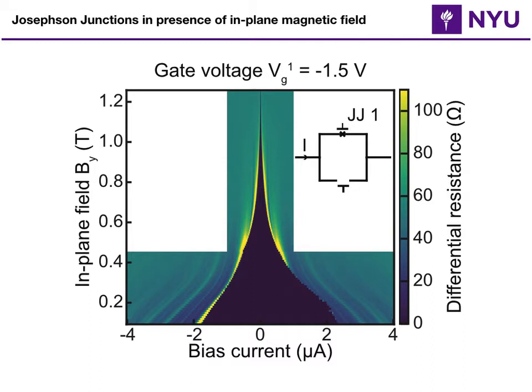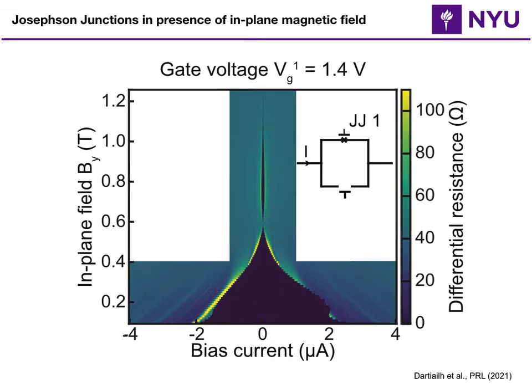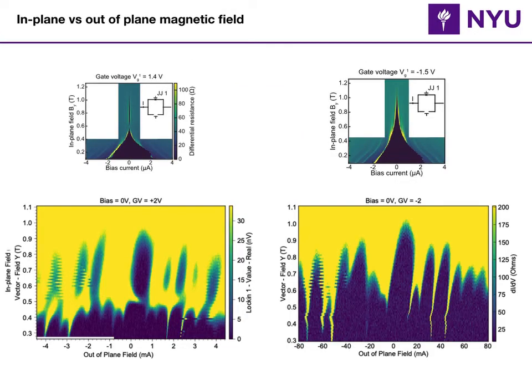In the same device, we can repeat this exact experiment by just changing the gate voltage to a higher value where we have substantial spin-orbit coupling. By increasing the gate voltage from minus 1.5 to plus 1.4 and repeating the experiment, you can see that the supercurrent closes around 0.6 Tesla and reopens and continues up to 1.2 Tesla, which is the critical field of the junction. So let me put this side by side again. The left side is where we have a transition. The right side is where we do not have a transition, right?